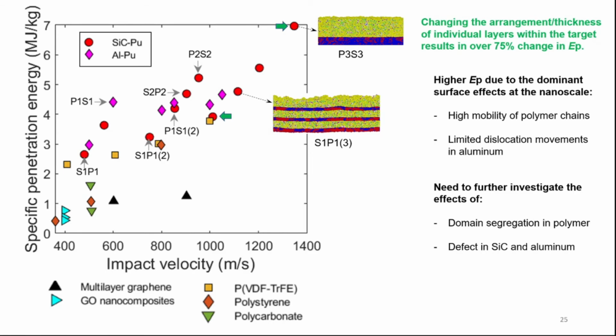This observed higher specific penetration energy of the multilayers can be mainly attributed to the dominant surface effect at the nanoscale. For example, the higher mobility of polymer chains near the surface helps the polymer chains absorb more energy. And also the free surfaces and interfaces of aluminum make dislocation movements harder.